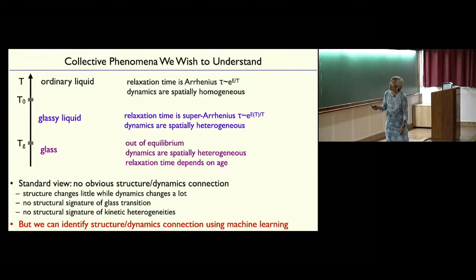But it's just the expected Boltzmann dependence of the relaxation time on temperature. If you go below something called the onset temperature, the relaxation time develops a stronger than Boltzmann-like dependence on temperature, as if the energy barriers are getting higher as you lower the temperature. Also, the dynamics become spatially heterogeneous. And then below this, there's a glass transition where the system falls out of equilibrium.